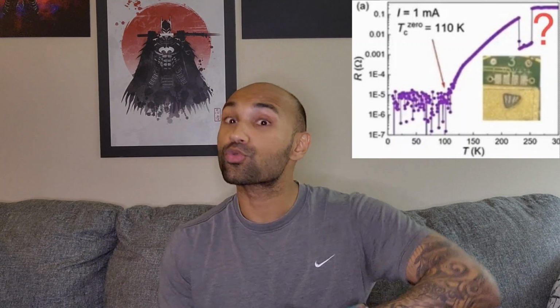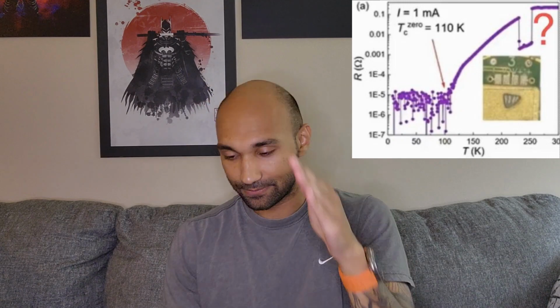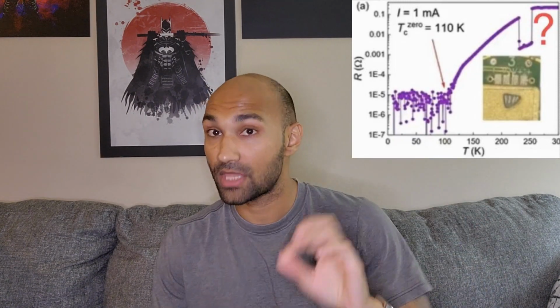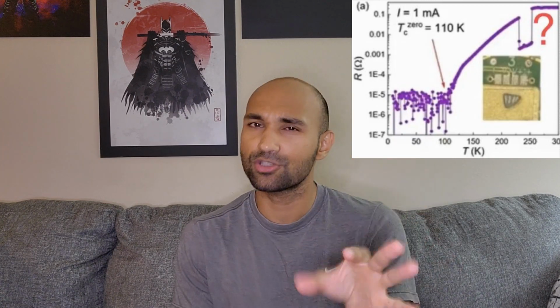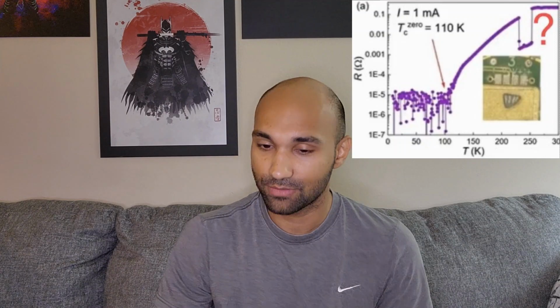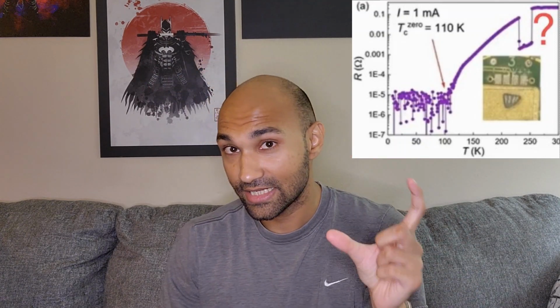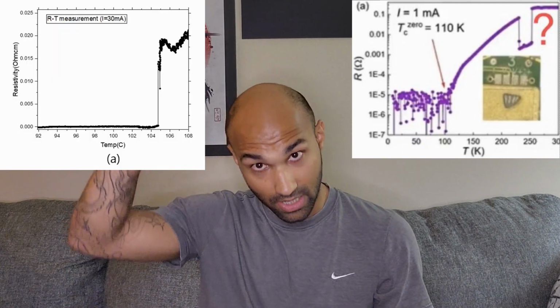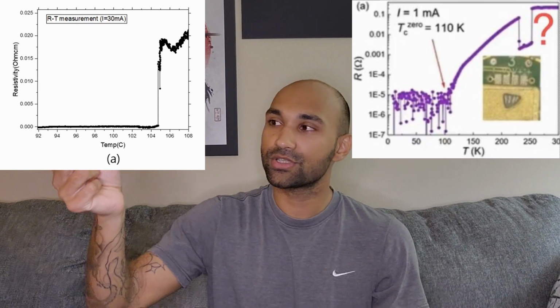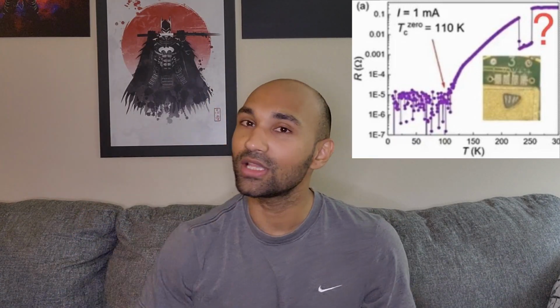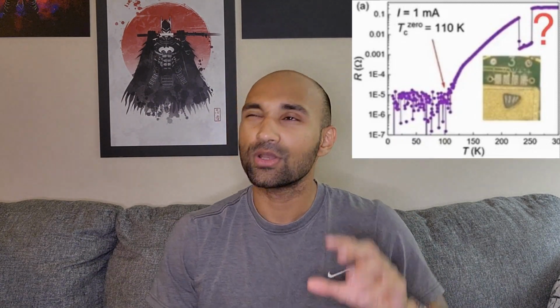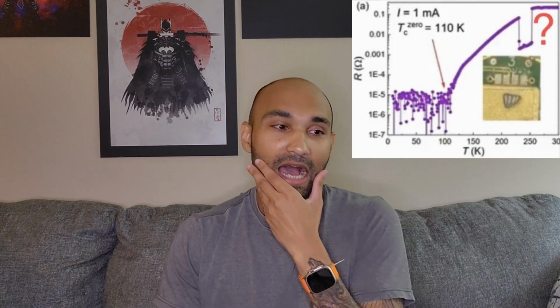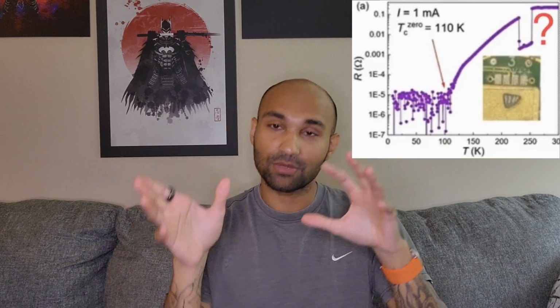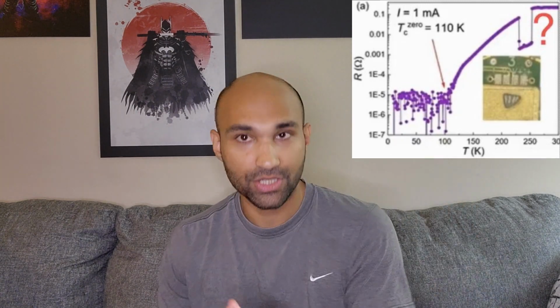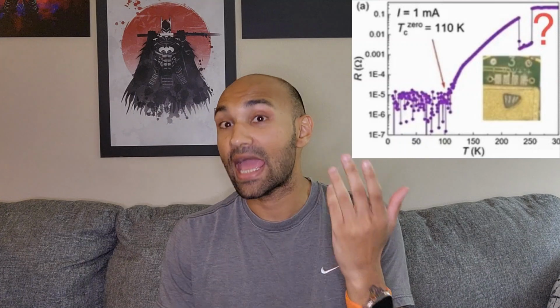It did not, because it comes right back up shortly after that and continues this descent that never has a sharp drop that you normally expect for especially type 1 superconductors. Type 2 superconductors sometimes have a mixed state. We'll come back to that near the end. In the original LK-99 paper, the Korean paper, they did observe a relatively sharp drop. It wasn't like that, but it was pronounced. Whereas in this, it just slowly came down to a resistance of, it should be noted, about 10 to the negative fifth or negative sixth ohms, which is what they report as near zero. Remember, as we talked about in the previous video, that superconduction doesn't necessarily imply absolute undetectable resistance. It is near zero, and this is what they're reporting as near zero, but once again at 110.